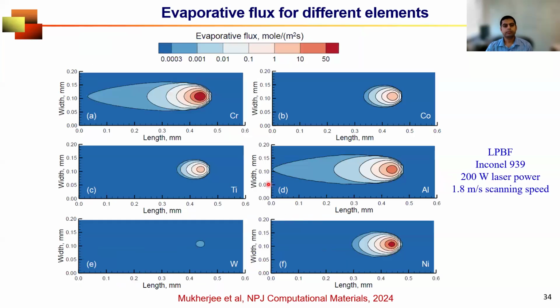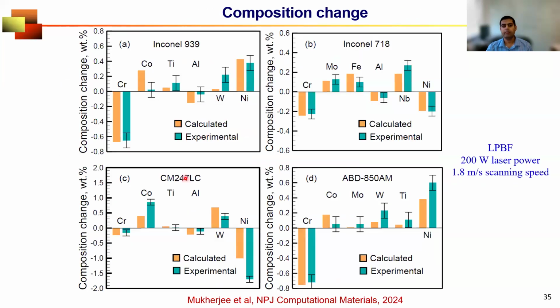And you see, for a nickel alloy, a nickel-based superalloy that consists of many elements like chromium, cobalt, titanium, aluminum, nickel, tungsten, we can calculate their evaporative fluxes. And depending on the relative difference of evaporative fluxes, we can find out the composition change, which is very consistent with the experiments that we performed for a wide variety of elements.